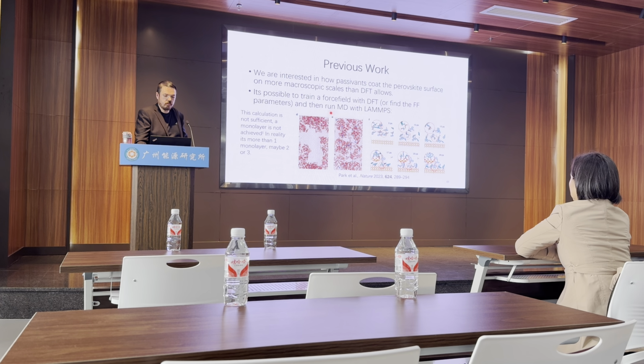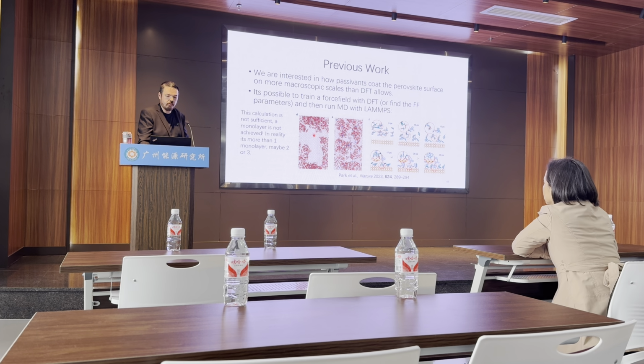So they added the coSAM and they get sort of covering, but visually it seems like it's not enough material. But what turns out to be the problem is if you try to do this by hand, it aggregates, the SAM aggregates. So you need a lot of SAM to get coverage. And a lot of SAM is actually what the case is in experiment. And experimental guidance helped us here a lot.